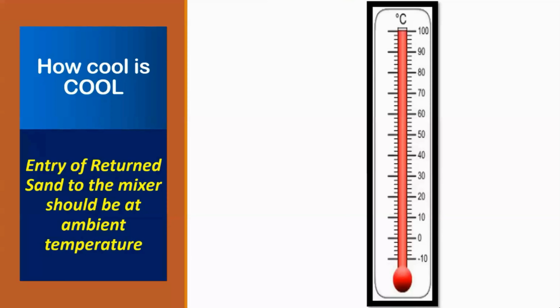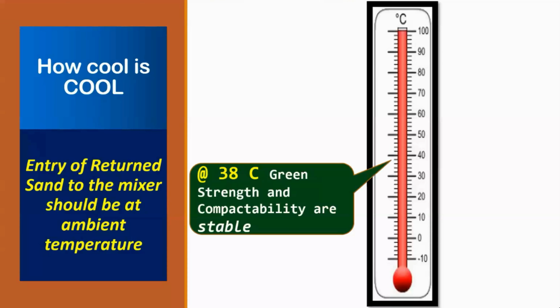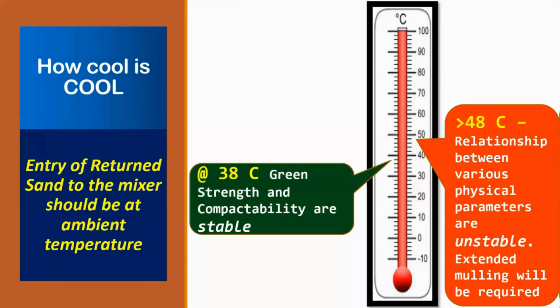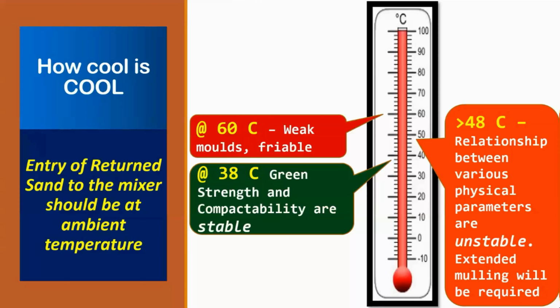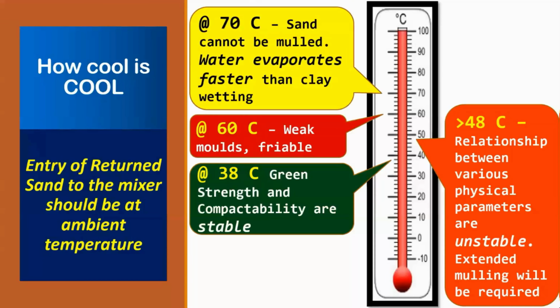So what has this temperature got to do with making molds? At 38 degrees, when you prepare the sand, all the sand parameters are stable. But when it reaches above 48 degrees, all the parameters become unstable and you require a lot of time to mull the sand. And when it reaches 60 degrees and you make the molds, they are very friable and very weak. And if the temperature of the sand is 70 degrees, you just cannot mull the sand. As you add the water, it will evaporate.